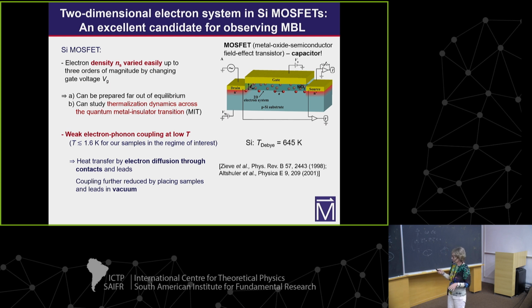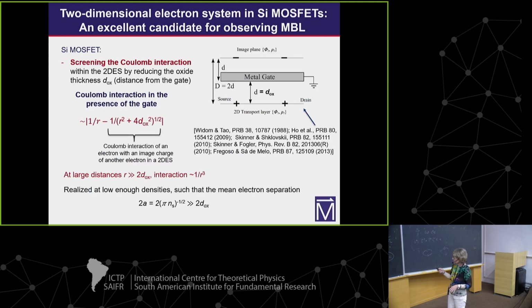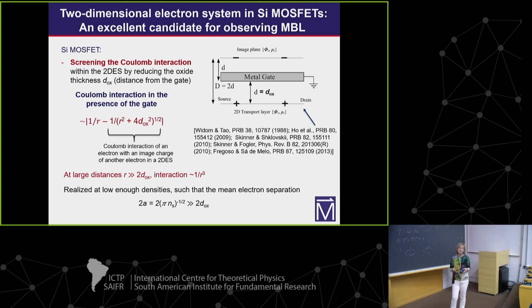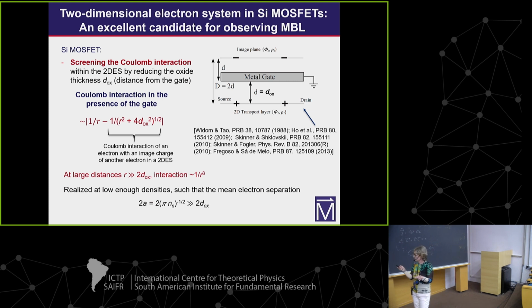So the system is weakly coupled to the bath. The other thing is we can investigate the effect of the range of the interaction by looking at silicon MOSFETs with different oxide thickness. It is known that the gate will screen the Coulomb interaction in a 2D layer, and if the mean electron separation, which is the case at low densities, is larger than the oxide thickness, then the Coulomb interaction is reduced to a dipolar interaction.